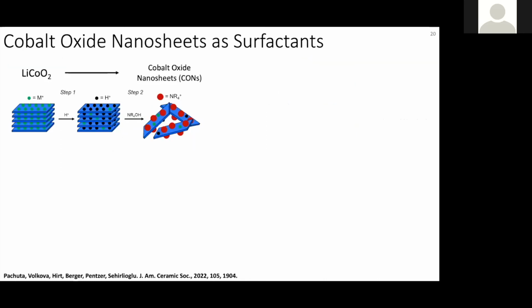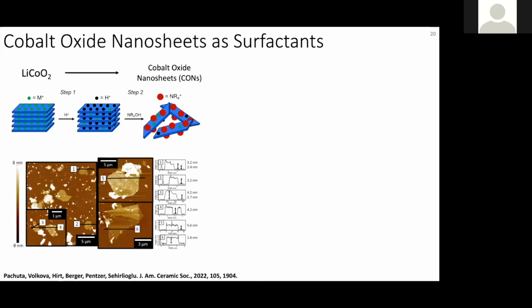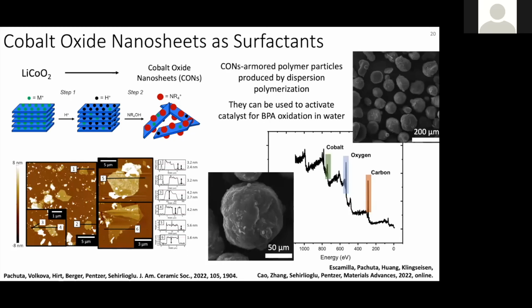And so we're also using cobalt oxide nanosheets. With Sehirlioglu at Case Western, we've developed chemical methods for the exfoliation of cobalt oxide nanosheets. We can make larger nanosheets than we could before. We can also make these cobalt armored particles and use these to activate a catalyst for oxidation of bisphenol A in water.